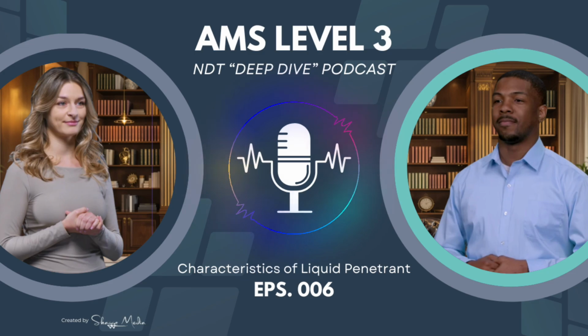But wait, there's more. The developer particles also play another scattering role. They scatter the incoming ultraviolet radiation throughout the penetrant seepage layer. Why is that important? Because in these microscopically thin seepages, the UV light might just pass straight through without much being absorbed on the first pass. By scattering the UV within the layer, the developer ensures that pretty much all the UV energy gets a chance to be absorbed by the dye molecules, even in a tiny amount of penetrant. This maximizes the amount of visible light that gets generated in the first place, so it boosts emission and escape.